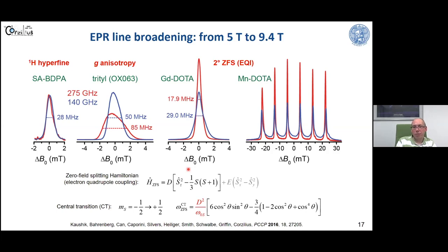And then you cannot sweep to this resonance. Cobalt, similar. Low spin cobalt 2 plus is also a spin 1/2 and has a g anisotropy that would typically be between 1.8 or 1.9 and, I think, up to 2.7. There's a very large g anisotropy, very large in relative terms. Of course, if you look at lanthanides, for example, this is much, much larger. And I will show, I think on the very next slide, a couple of examples of these lanthanides. Cerium, for example, is also a spin one half system where you can have g factors which approach zero or even infinity.